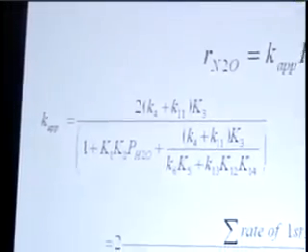And before that, I'll show you the rate expression that you can get. It's consistent with experiment. It's first order in N2O. The apparent rate coefficient is anything but simple. It's shown over here. And hidden in here is a dependence on water. It was not obvious when we started that there would be this dependence. And as I'll show you, this water dependence provides the explanation for the huge disparity in things that experimentalists, including ourselves, have reported. But before we get there, I'll just remind you that this approach works very well.